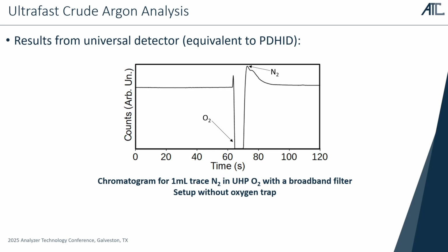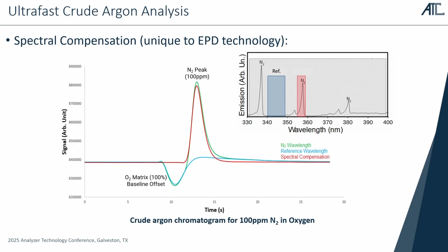Here you have a result from a universal detector, and you can see that it can be quite hard to separate the nitrogen from oxygen here. So why we developed the spectral compensation method to have this fast analysis is that we can measure two different wavelengths, one that is highly sensitive to nitrogen, and the second that is only sensitive to the background level. And what we can do is combine these two wavelengths to get the red chromatogram here, where we compensate the baseline to get a clean peak from nitrogen that can be easily integrated.